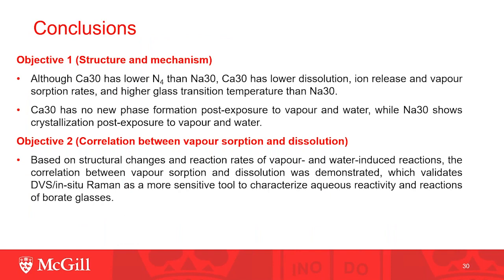Based on the experimental results, we conclude: first, although calcium-30 has a lower N4 than sodium-30, calcium-30 has a lower dissolution, ion release, and vapor absorption rate, and a higher glass transition temperature. Second, calcium-30 has no new phase formation after exposure to vapor and water, while sodium-30 shows crystallization after exposure to both vapor and water. Third, based on the structural change and reaction rates of vapor- and water-induced reactions, the correlation between vapor absorption and dissolution was demonstrated, which validates DVS and in situ Raman as more sensitive tools to characterize aqueous reactivity and reactions of borate glasses.